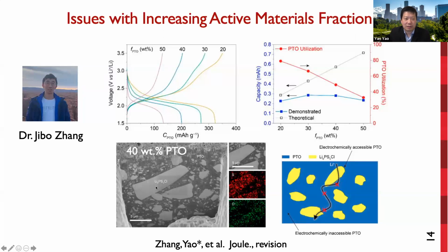Electrolyte islands with size between 2 to 15 micrometers were surrounded by a sea of PTO and carbon mixture. Such a microstructure is unfavorable for lithium ion transport because the electrolyte couldn't find the percolation network, and the PTO has a lower ionic conductivity for lithium ion transport. The reason for forming such an undesired microstructure is related to the soft and compliant nature of organics. Organics deform easier before the lithium ion solid electrolyte deforms.